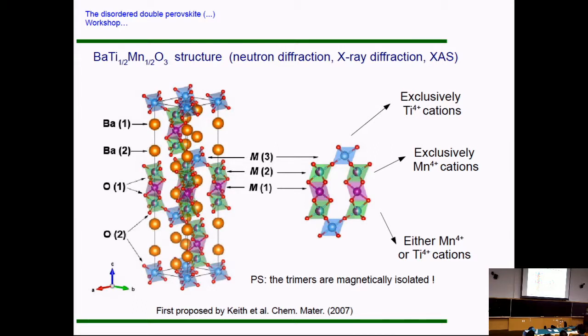And then I say this is a disordered double perovskite. I'm talking about the mixed occupants here of this M2 site. So as you can see in this proposal, all the manganese cations are within these structural trimers. So all magnetic properties come from these structural trimers. You should expect a very strong first neighbor interaction here, but the trimers will talk to each other only by means of this exchange path here or by direct exchange.